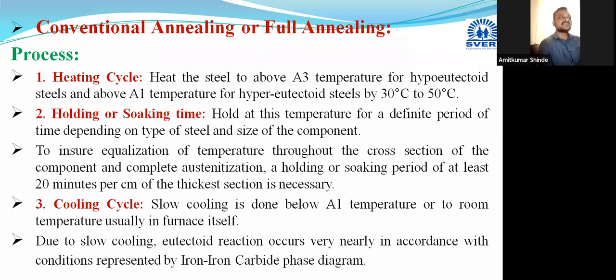And at this particular temperature, depending on the type of steel and the shape and size of the component, we are providing some holding time or soaking time. Why are we providing this holding time or soaking time? To ensure the equalization of the temperature throughout the cross section of that component, and we will get homogeneous austenite, meaning complete austenitization will occur. That's why we are providing this holding time. Generally this holding time is at least 20 minutes.